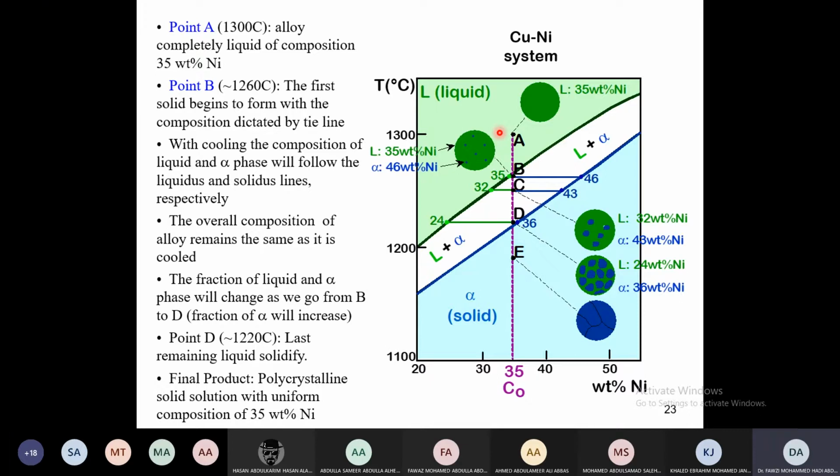Of course, which spots will start that? It will be the coolest spot in the material, because as we have already mentioned in chapters 3 and 4, the temperature is not homogeneous across the material. Was the temperature homogeneous? No, it's not, and that's why the coolest spot will start to nucleate a solid grain, and then the next coolest, and then the next coolest, in different areas of the material.